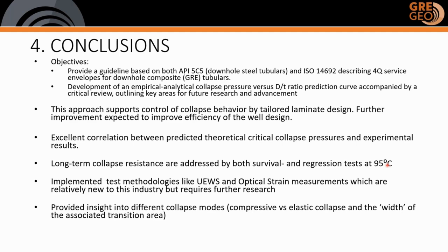We found an excellent correlation between the predicted theoretical critical collapse pressures and experimental results. Long-term collapse resistance is validated by both regression and survival tests at 95 degrees C. We included test methodologies relatively new to this industry, like UEWS and optical strain measurements, but concluded that these techniques still require further research. The project also provided insight into the different collapse modes and the width of the transition area between these modes.